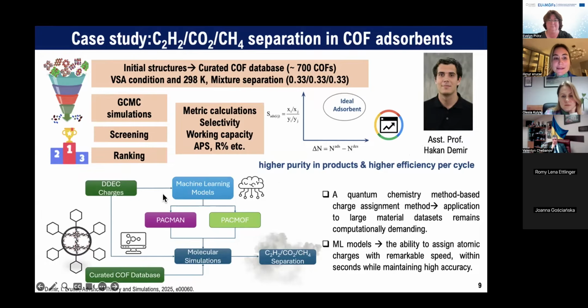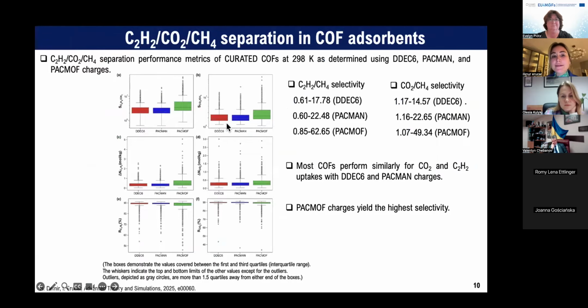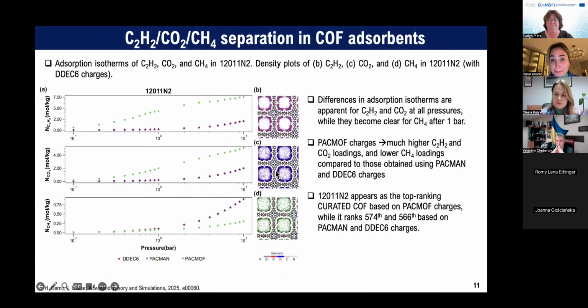So here we tested the charge assignment methods when we ranked the materials. What we did is, let me show you. We selected Pacman and PACMOF charge assignment methods. These are machine learning models, by the way, and DDEC6 is the accurate charge assignment method. You can use it, the DFT-based method. In this work, here you can see the selectivity, the working capacities, and the R% regenerability values for the COF structures. And we found that most COFs, for example, perform similarly for CO2 and acetylene uptakes when you use the DDEC6 and Pacman charges. On the other hand, PACMOF charges yield the highest selectivity.